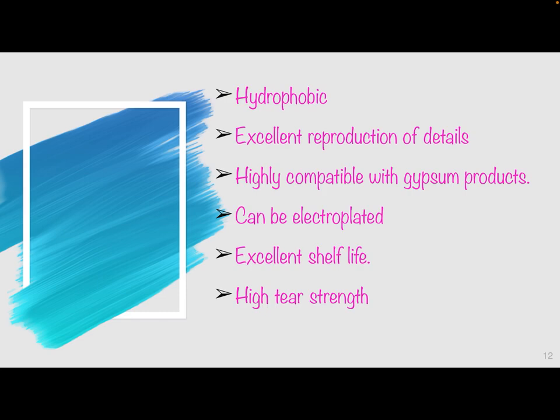Looking closely at the properties, the polysulfides have a working time of about 4 to 6 minutes and a setting time of about 12 to 16 minutes. They have a permanent deformation of 2 to 3% when held under 12% compression for 30 seconds, and a shrinkage of about 0.3 to 0.4%. So it should be poured immediately. It is hydrophobic in nature and has excellent reproduction of details.